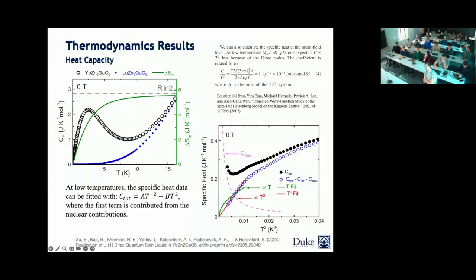Now, when we are dealing with rare earth elements, specifically ytterbium that has a lot of isotopes, you will expect some sort of hyperfine interactions due to the nuclear contributions. So this is basically what we are showing, a contribution from the nuclear hyperfine. And we subtracted this off, as well as the phononic term, which is very negligible in this case. And this is what we've extracted.